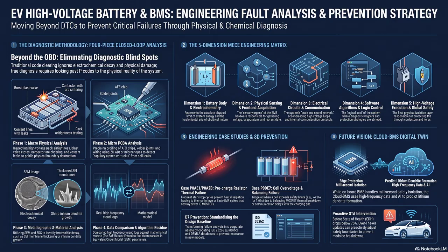Yeah. If you pull up to a 250 kilowatt DC fast charger in the dead of winter and try to force massive amounts of energy into that freezing battery, the lithium ions can't slide into the graphite seats fast enough. There's a bottleneck at the entrance. Exactly. Because they can't get inside the anode, the lithium ions start piling up on the outside surface of the anode. And as they pile up, they begin to bond together, forming pure metallic lithium. And this process is called lithium plating.